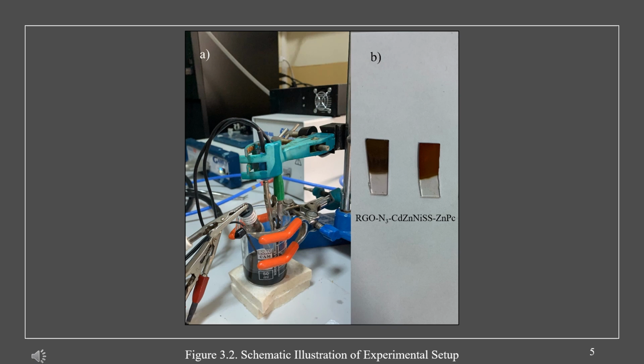During the process, thin films were generated by electrodeposition with cyclic voltammetry. First of all, the ITO to be used as the substrate. The washing procedure was briefly as follows. First, the ITO is taken into a glass beaker and washed with detergent water. Secondly, washed with ethyl alcohol and mixed in an ultrasonic bath. And finally, the procedure is completed by washing with distilled water.